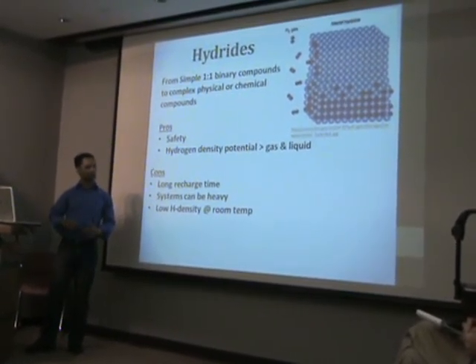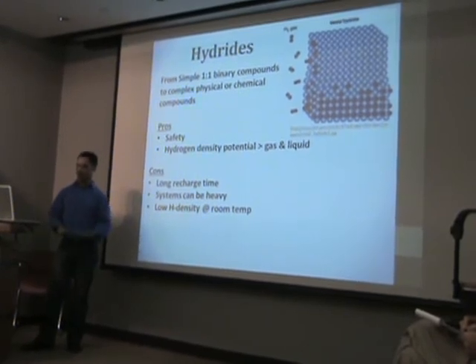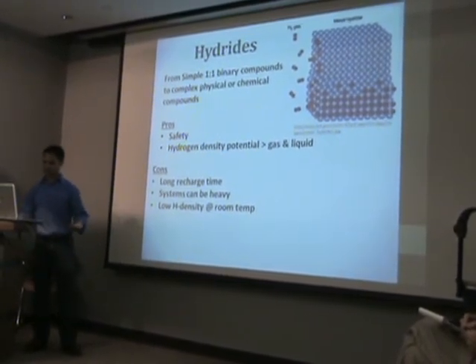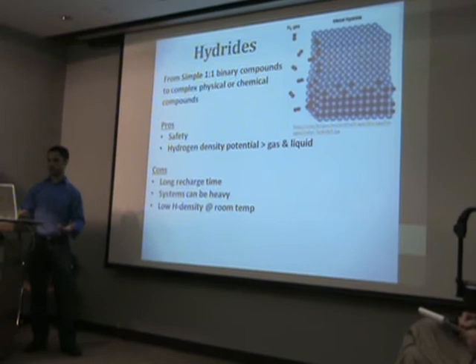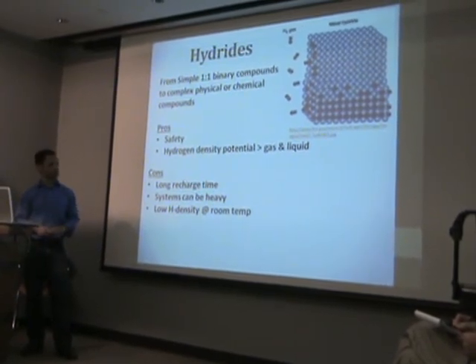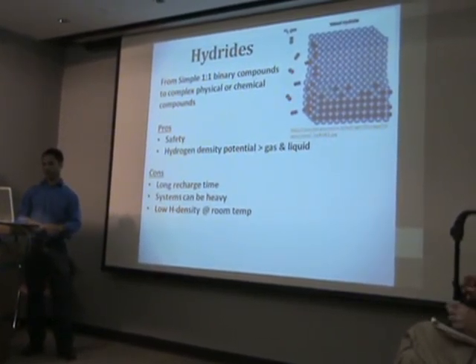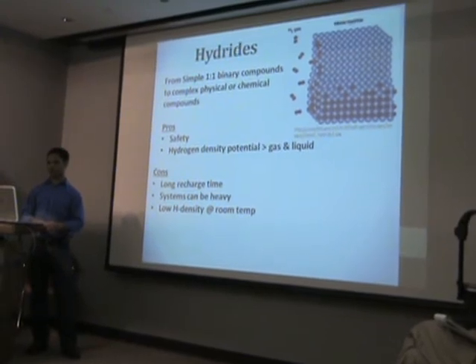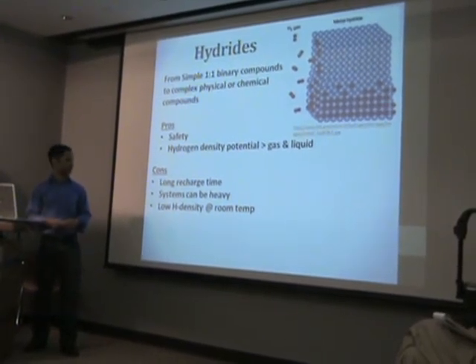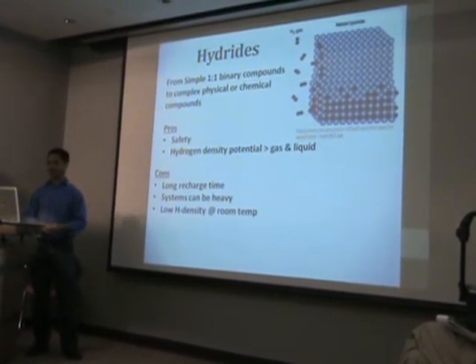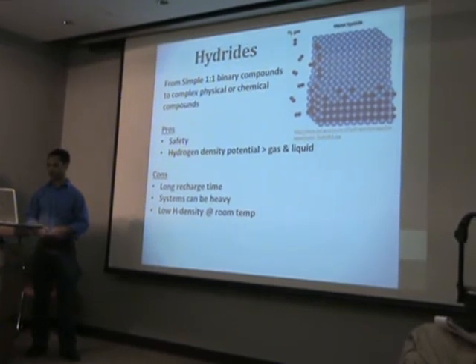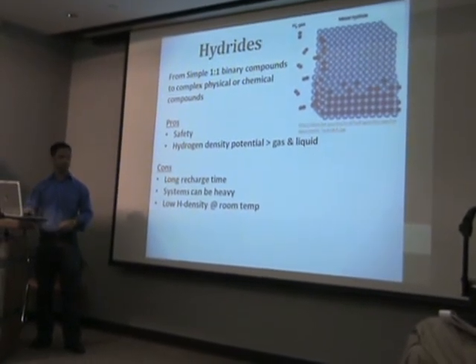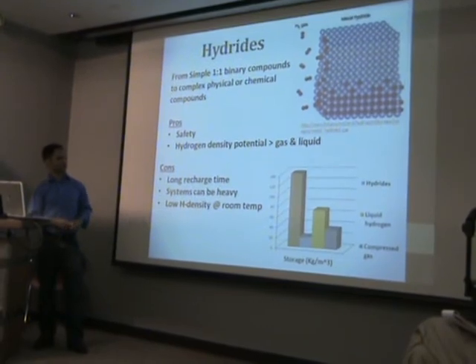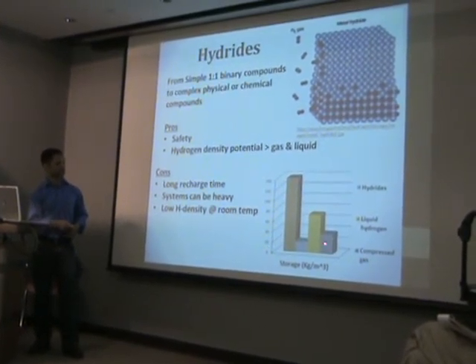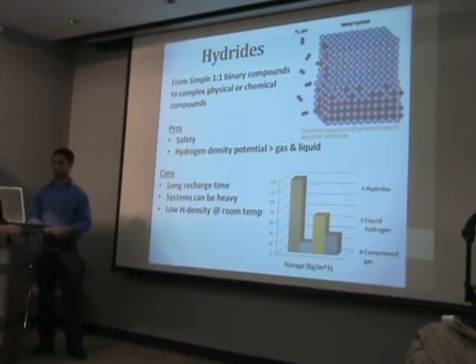If you replace an entire gas tank worth of gas in a car, which is 4 kilograms of hydrogen, and get the same travel distance, but with a hydride, that 4 kilograms of hydrogen is going to make the system weigh twice as much as the original gas tank. And the recharge times are long, like 24, 48 hours. Probably the biggest drawback is where it falls on the chart, right there. Kind of pathetic. It's like 2% density per weight.